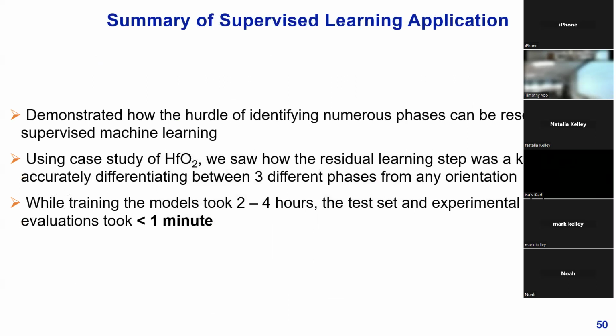And so the summary of this work is that we were able to demonstrate how the hurdle of identifying numerous phases from any orientation can be resolved using supervised machine learning. And in this particular test case of hafnium oxide, we saw how residual learning was a very key aspect of being able to accurately differentiate between three different phases. And while the training of the models took a few hours each, the actual evaluations for every experimental data set was less than a minute each time.